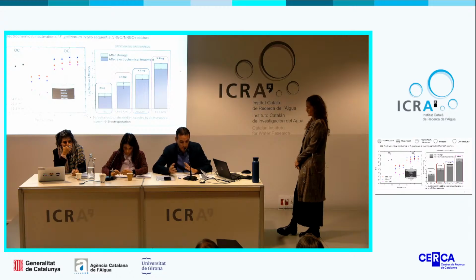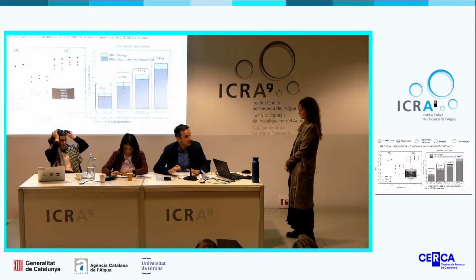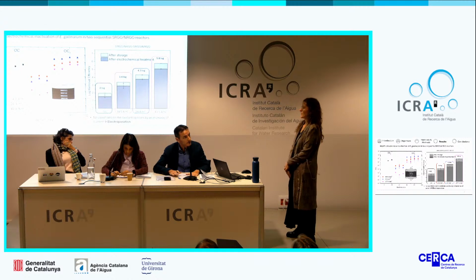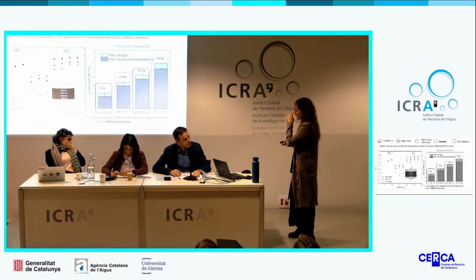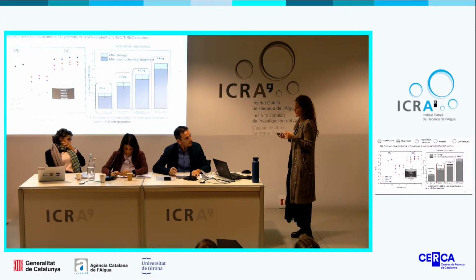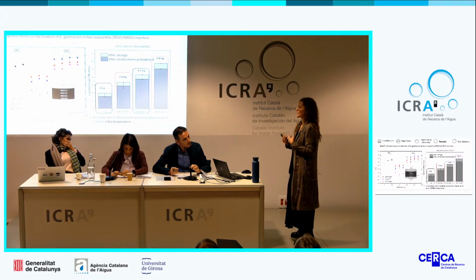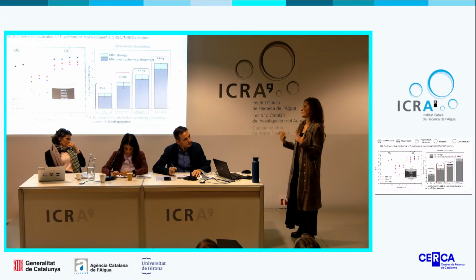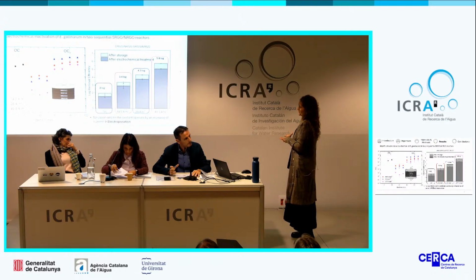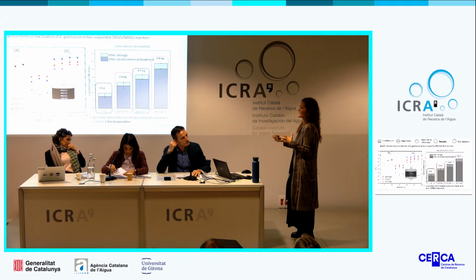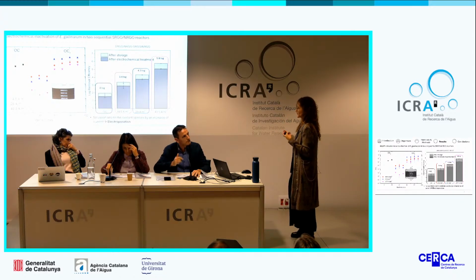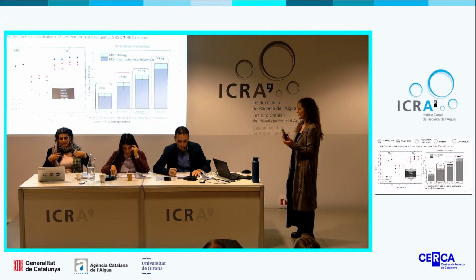No, I could understand this if the mechanism is an oxidation or electrooxidation that requires the adsorption of the pollutant. But here you are always mentioning ozone. I have understood that it is the main oxidant also because it's the most concentrated that you are generating. So ozone-mediated oxidation seems more important than hydroxyl-mediated one, right? Well, but ozone is sometimes also activated into hydroxyl radicals. The kinetic rates of some of the pollutants are not that high with ozone compared with hydroxyl radicals, which means that they are more easily attacked by hydroxyl radicals than by ozone.